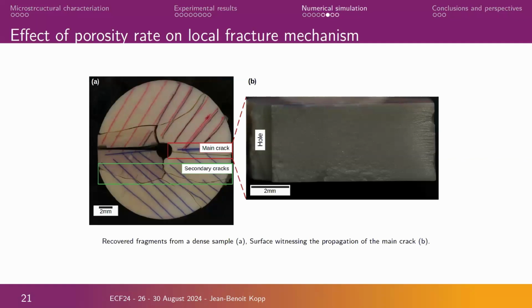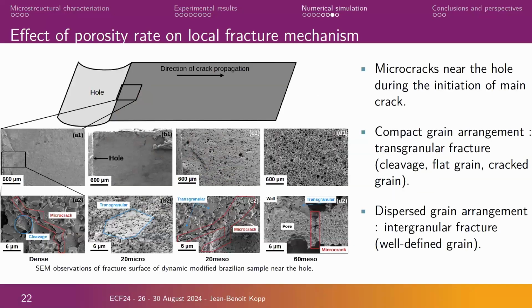Another last thing, maybe in this presentation, is about microstructure and fracture analysis, because post-mortem, is it possible to refind all pieces of the specimen? Because we have all in the small box during the propagation, and it is possible to reconstruct the specimen and to try to find the main crack and to follow the fracture mechanism locally. So we have made different observations with electronic microscope. So just near the hole in the crack initiation, we can observe some specific mechanism just over there with microcracks near the hole. And of course, classical transgranular and intergranular fracture.